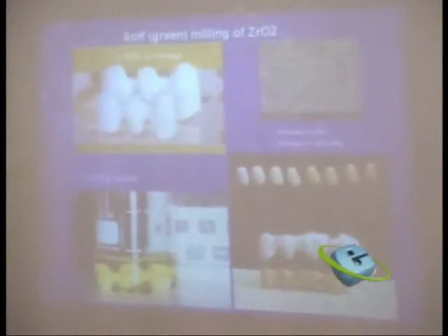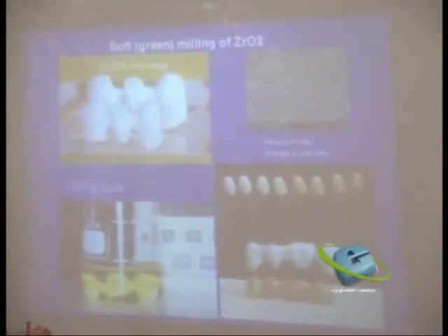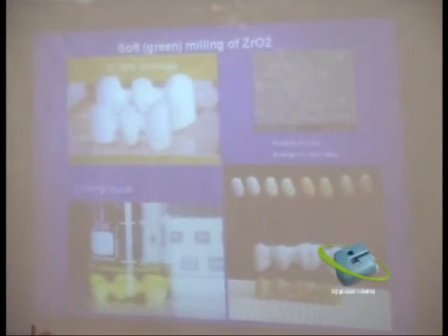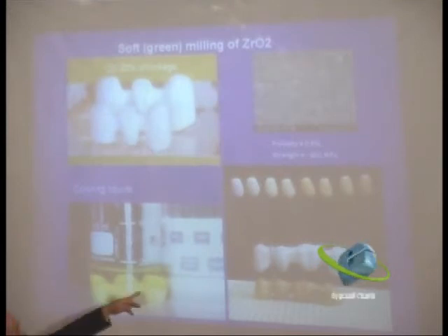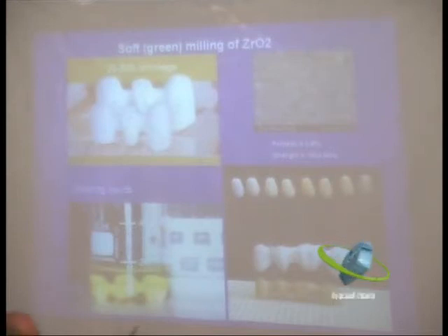And so we can do this with systems, and this is very common now, where different companies have got these devices. There is now availability of colouring liquids, usually iron-based, such as iron chloride and iron nitrate, and the material is dipped in these systems. Depending on how many dipping processes, you can change the value of that material to match more closely the type of features that you want. And you see here this dramatic change in the colour, from these very tombstone white colours to much more realistic mouth colours.